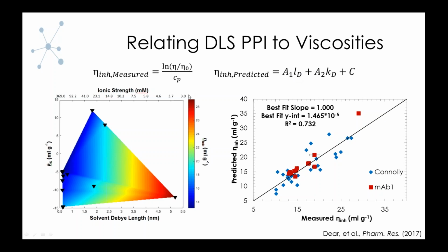That's directly calculable from the ionic strength, which can depend on the concentrations of the co-solutes and how charged they are. The idea is that if you have the same measured KD for two systems of varying ionic strengths, the one with the shorter Debye length is going to have more repulsion screened out of it.